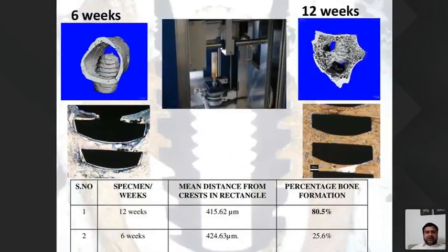Now, we went ahead with a histomorphometric study also. There's a very complicated processing for a histomorphometric study, especially in the case of an implant along with the bone. So they took a good 48 days to process the sample, and it confirmed our findings of micro-CT, where we had a good amount of bone at 12 weeks. So at 6 weeks, we had around 25.6% of bone formation that you could see on the lower left side, right here. And in the lower right corner of the histomorphometric picture, you can see the bone forming all around the threads of the implants. Now, this was about 80.5% bone formation. In the middle picture, you see how the sample is put in the machine for analysis in micro-CT.